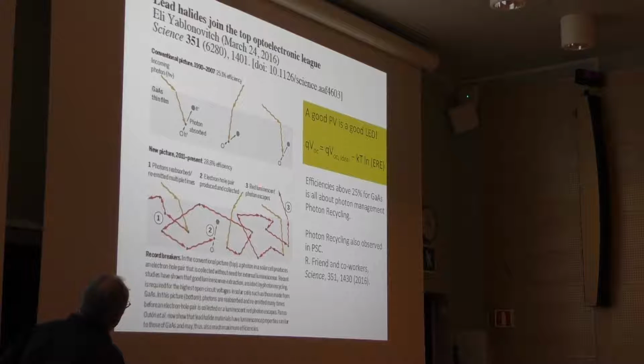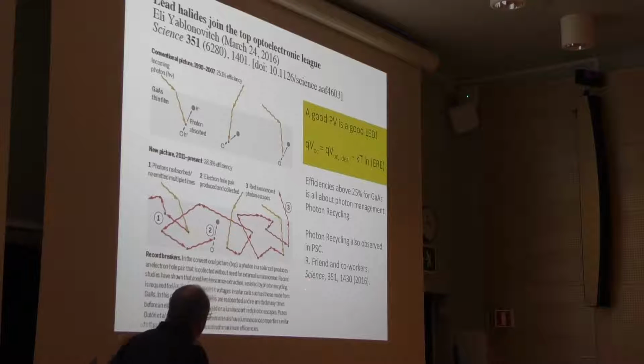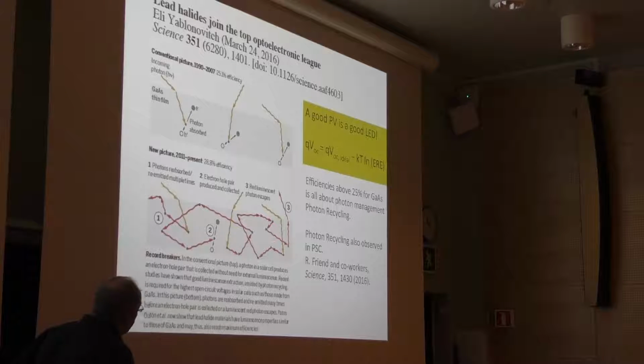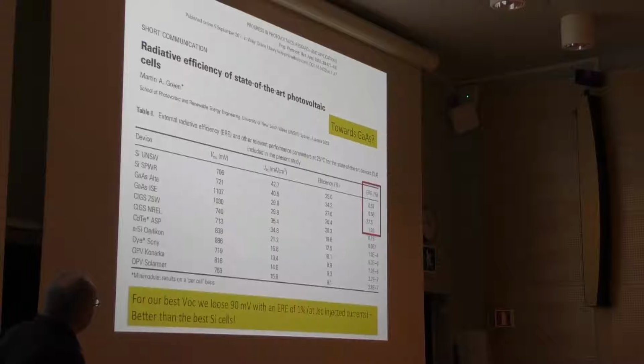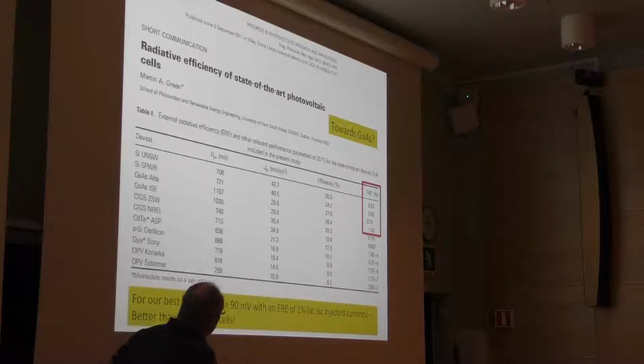And the reason is something called photon recycling. What you can do in photon recycling is that you excite something in the layer of gallium arsenide or perovskite also. Then that can emit, if it has a high radiative recombination, it emits the photon and it can be reabsorbed within the layer and emit and be reabsorbed and so on. It's called photon recycling, and it was shown by Richard Friend and his co-workers this year that perovskite has this photon recycling mechanism as gallium arsenide has. Silicon does not have this. So this means that we can compare; this electroluminescence should be high.